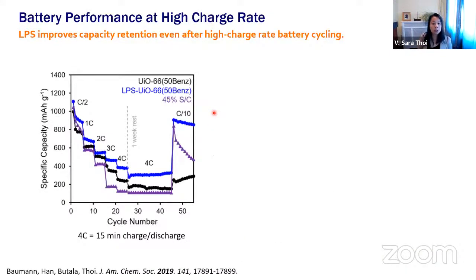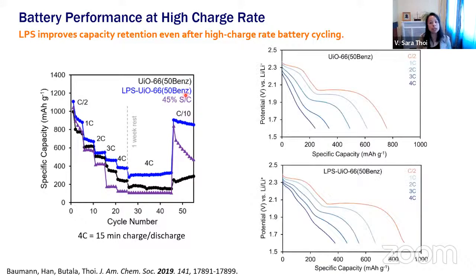We can also do some charge rate capabilities of our batteries, and in every case, from charging from 2-hour charges all the way down to 15-minute charges, we see that our functionalized metal-organic framework always outperforms our 2 other controls. And what's unique about this is that if you took a look at the galvanostatic discharge curves, you start to see some really interesting features.